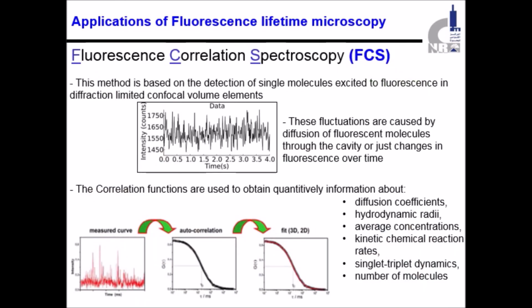The fourth technique is fluorescence correlation spectroscopy, or FCS. FCS is a high-resolution spatial and temporal analysis of very low concentrations of biomolecules. This is done by measuring the spontaneous intensity fluctuation caused by deviation of the system from equilibrium. It is based on detection of single molecules excited to fluorescence in a diffraction-limited confocal volume element. The produced spectrum appears as shown in this figure.